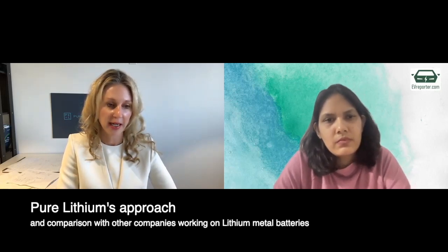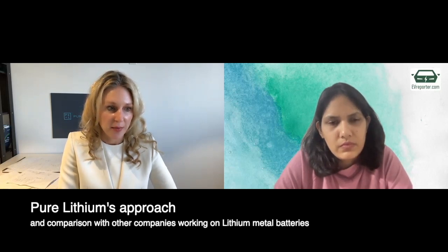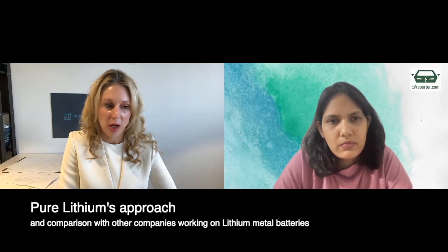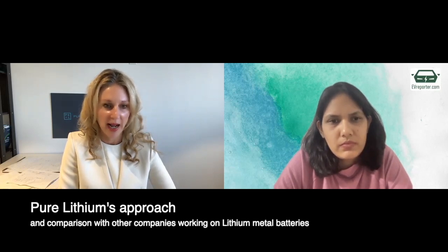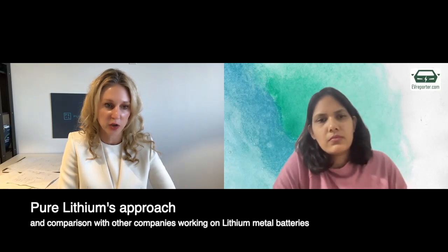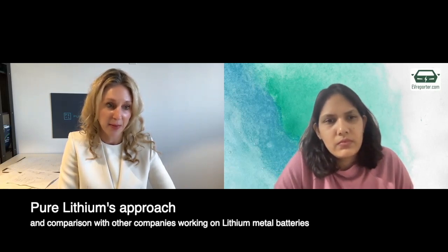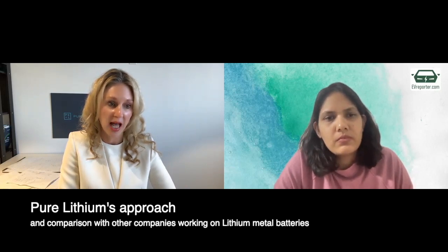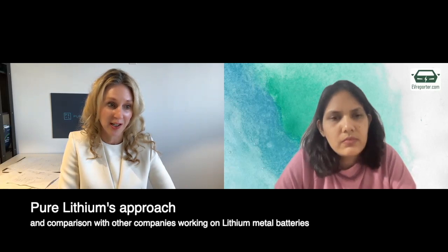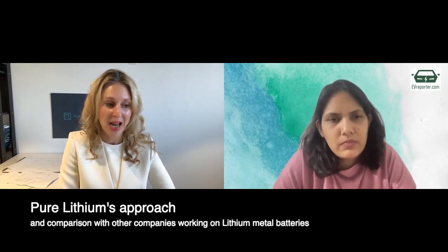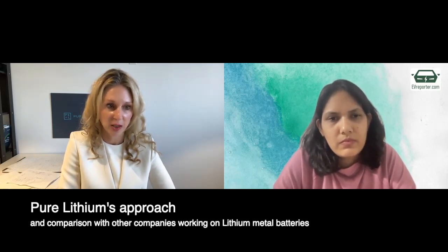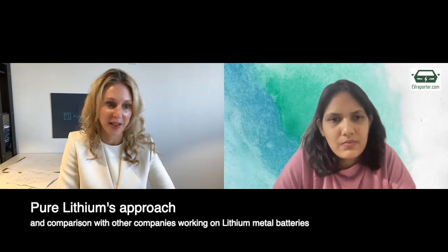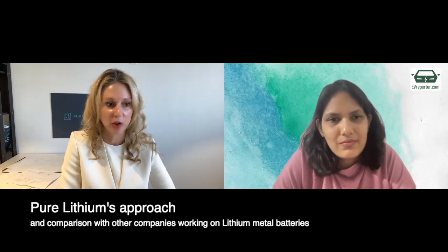And if you're using an organic electrolyte or any kind of aqueous system, the charge carrier per unit is so low and so sluggish, and molten salts, they're so highly conductive. So we have one in our lab that we use for extraction and one in the battery, and we have the temperature down to 68 degrees, and we're working on another salt that melts at 13 degrees. So we're very, very, very excited. These are non-flammable. So we want to debut a battery that is inherently non-flammable for electric vehicles. And we definitely have a long road ahead of us. The largest battery we've built so far is 50 milliamp hours, but it's a solid 2-layer full cell. We're really, really excited. Okay.